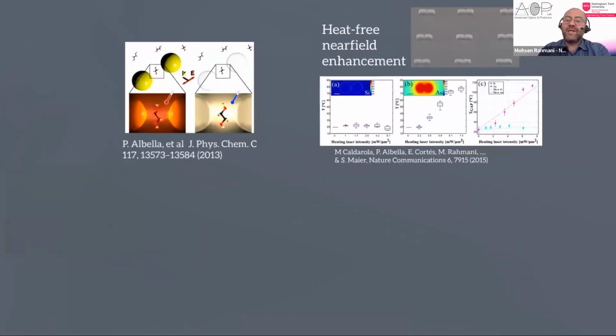So for the linear regime, just a second, please. For the linear regime also, we can have these nanoparticles next to each other, and we can also generate some hotspot and near fields. But the point is that in the dielectrics, the intensity of those near fields is much weaker than the plasmonic nanostructures. But the advantage is that because they don't absorb light, these dielectric or silicon nanostructures do not generate heat.